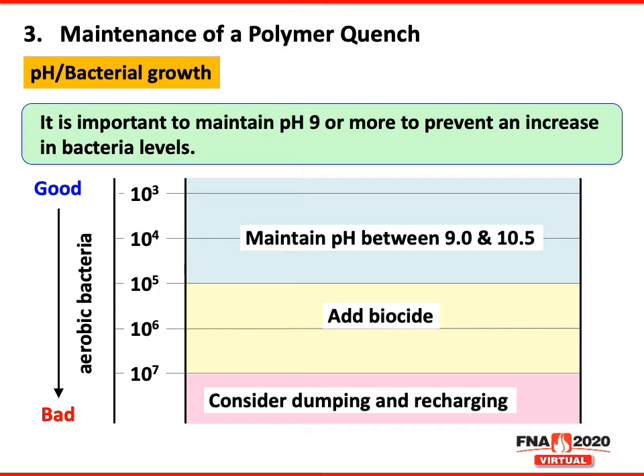So now if you have a pH issue, what do you do? Well, if you're between 9 and 10.5, you're fine. And you'll have small amounts of bacteria. Again, we're not trying to create a sterile environment. But as you start to get higher and higher in bacteria, that's when you may need a biocide, or you need to consider dumping and recharging.